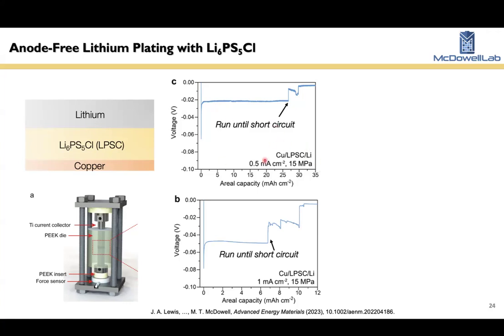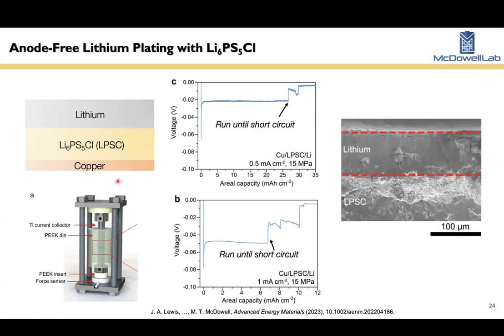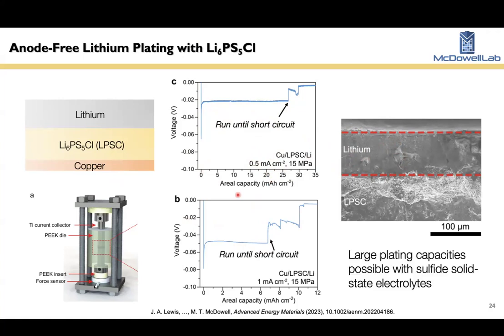Here I'm showing at a moderate current density, 0.5 milliamp per centimeter squared, we can deposit a lot of lithium onto a copper current collector. Here it's over 100 microns. And when we go to higher current densities, we can still deposit quite a bit of lithium, but we eventually run into short circuiting issues. So basically, if you are very careful about your cell construction, you can get good lithium deposition performance in these sorts of cells. So that's good.